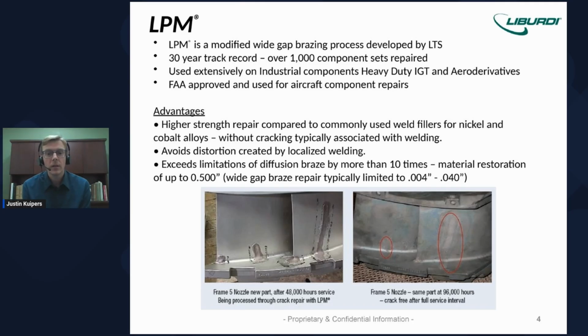What are the advantages of LPM in comparison to other repair technologies? So in comparison to welding, which is a commonly used repair technique for turbine components, LPM offers both improved strength over commonly used weld fillers, and it also eliminates or significantly reduces the cracking or distortion that occurs with welding. With welding, those are issues that are commonly encountered, and so that limits the size and the surface area that we can repair on components. Whereas with brazing and LPM specifically, it's a process that allows us to repair much larger surface areas, much larger crack sizes and defect sizes because it avoids the cracking and distortion associated with welding.